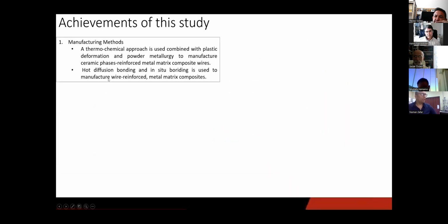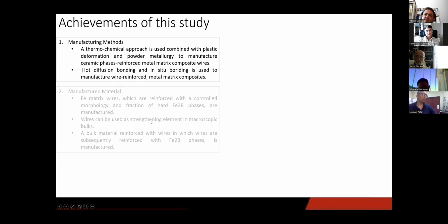Achievements of these studies: we have shown a manufacturing method, a thermochemical approach, which uses plastic deformation and powder metallurgy to make composite wires which are reinforced with ceramic phases. Hot diffusion bonding and in situ boriding is used for the first time to make wire reinforced bulks. No squeeze casting and no fiber foil type approach is used. So it is a new manufacturing approach.